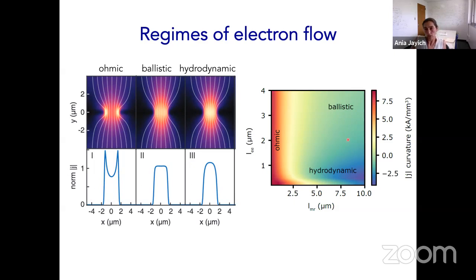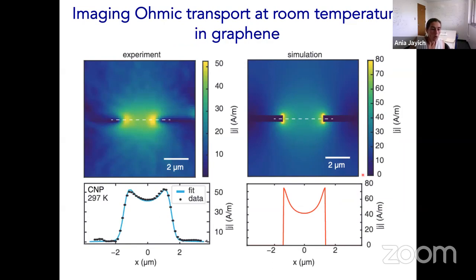And one can achieve these different regimes of ohmic, ballistic, and hydrodynamic depending on the relative values of the electron-electron scattering length, which is this momentum conserving length, and the elastic mean free path, the momentum relaxing length. And this is what is expected for our device geometry. This is where we expect to be in the ohmic regime, when electrons scatter quickly off of phonons. When electrons travel very long distances and have long electron-electron scattering lengths, we expect ballistic. And in this interesting regime down here, when electron-electron scattering length is short, but the momentum relaxing length is long, we expect hydrodynamics.